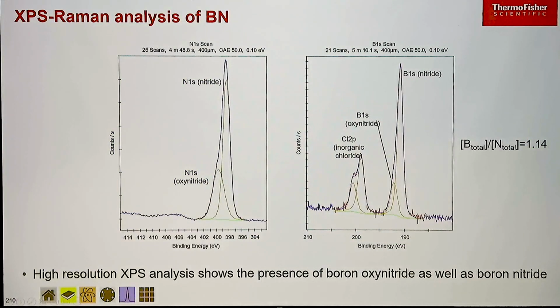And we can confirm it by checking the high resolution scans, and we see the intensity for boron at the nitride peak energy. There's a little bit of oxidation as well, so we see a little bit of boron oxynitride. And again, in the nitrogen signal, we see a peak for nitride, and a peak for oxynitride as well.